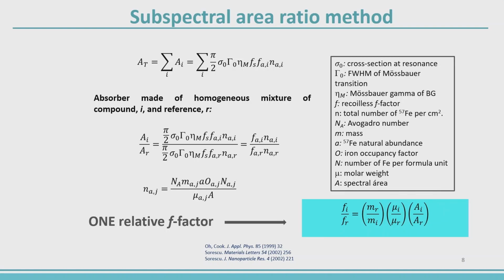It is a sum of the area components. Here, i is the iron sites of the compound, or if we have a mixture of two iron compounds, then it is a sum over the phases that are here. This formula is already known from the literature, so it's not new. It had been used a long time ago, but I want to point out that in this formula it is useful to determine the recoilless F factor relative to the recoilless F factor of a reference compound. The reference compound here can be metallic iron powder, or hematite, well crystallized hematite.